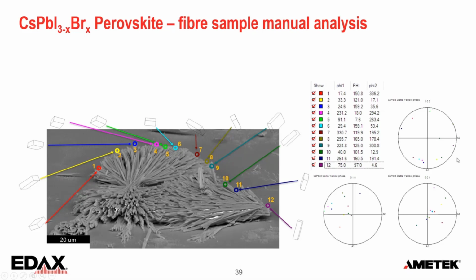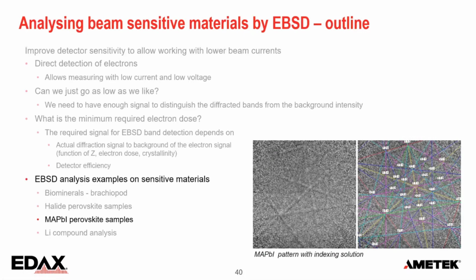And also here I have a fiber texture, well, fiber texture may not be right, but you can follow the bundle in the orientations here of the C-axis. The A-axes are all around the circumference again, just like we saw before. And here also the B-axis is pointing outwards. So even on a sample like this, where mapping is not possible, there's still a lot of very valuable information to be had. Now let's go to a little bit more challenging material.